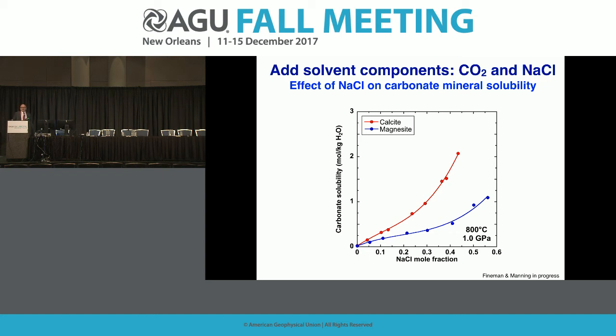And we actually think we're sensing two fundamentally different regimes in the fluid phase through these kinds of experiments. We're seeing in the region where the curvature is tailing off as NaCl concentration increases, this is calcite and magnesite dissolving as the familiar ions that we all know and love, bicarbonate and other hydrates. Whereas at higher concentrations, the species that are present in the solution are essentially anhydrous. It's the only way that solubility can increase as water activity decreases with rising NaCl mole fraction. And so in the light blue region, we have a region where standard approaches in aqueous electrolyte geochemistry are relevant and appropriate for describing these fluids.